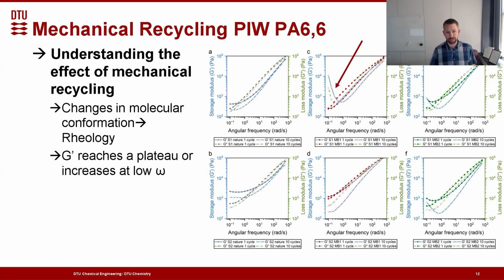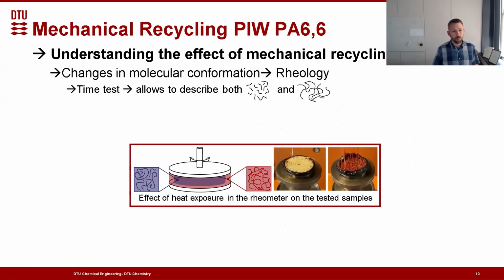So in this case, this is a 10 times recycled red sample that clearly shows a degree of cross-linking after reuse. What happens in these systems is that the system gets affected by the heat and exposure that we have in the rheometer, where we clearly see, when we look at the samples, cross-linking taking place on the outside of the sample. So this is very easy to observe on the samples, but it's also a very nice way to have something that's extremely sensitive to changes in the material, and therefore allows us to monitor what happens with the system over time.